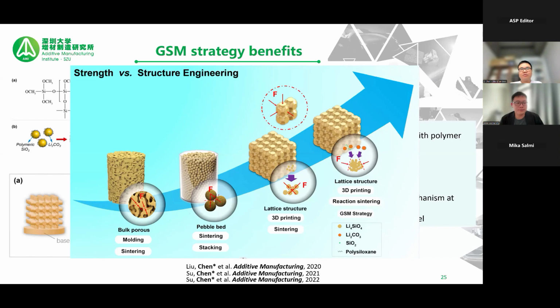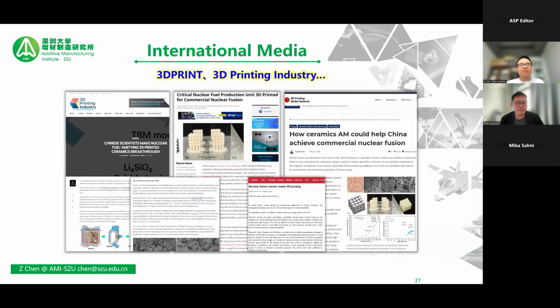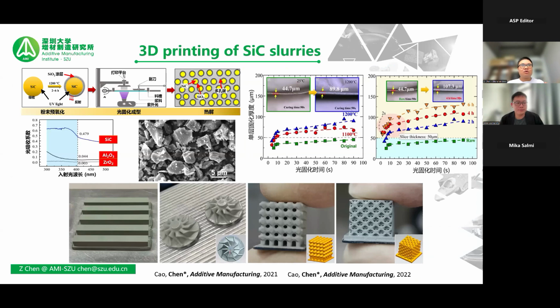So for silicon carbide material, if you want to use photopolymerization, it is much more difficult than for oxide materials, because silicon carbide has a large absorption coefficient of light compared to alumina and zirconia, like 10 times even higher. So it's hard for them to be photopolymerizable. And what we propose is a kind of pre-oxidation. It means heating in air or even in an oxygen atmosphere, and then there is formation of very, very tiny thin layers of silicon dioxide coating. So these kinds of shell coating structures can improve the